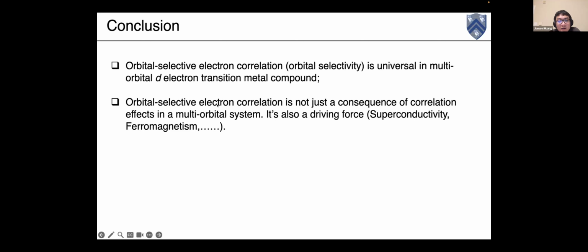The other thing that I think I learned is that this orbital selective electron effect is not just a consequence, or not just a phenomenon, of the correlation effect in a multi-orbital system. I think it's also a driving force. So it can induce these Fermi surface reconstructions, and it can pin the flat band to the Fermi level. Then it can be more related to the superconductivity and the ferromagnetism or other exotic phenomena in these material systems.